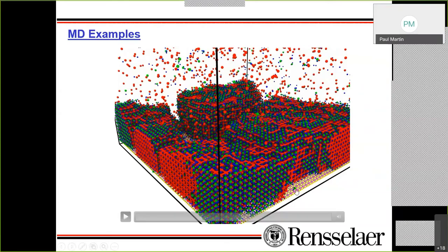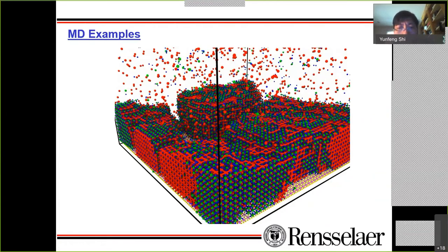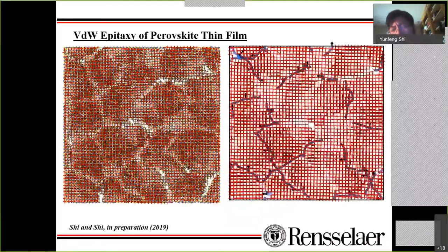Thank you. All right. So now you can see that I basically built the bond between the vertices of the cube, and you can see the perovskite structure. So now we can go ahead and do analysis of this really complicated structure of the perovskite thin film. What you can see is that we can identify all the dislocation lines, the misfit dislocation lines around here. Here is one dislocation line, here is another, and very importantly, we can identify the misfit dislocation, but also the threading dislocation.